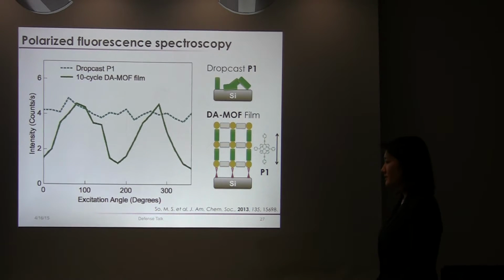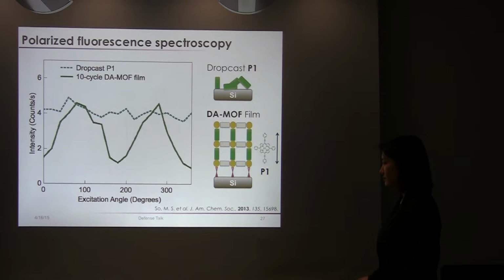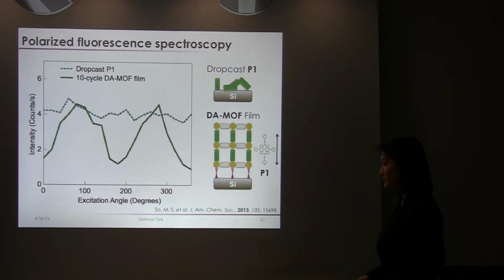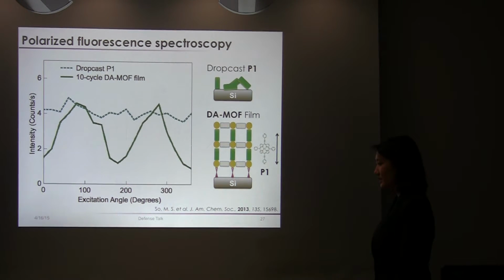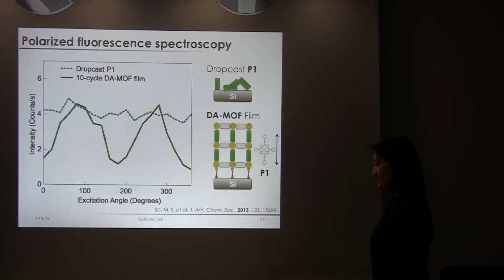So in the first couple layers, I guess between 0 to 10 cycles of film growth, by SEM I see just regions of nucleation. But after that, this film growth merges into a film growth region. So after that, I see that more homogeneous film growth is occurring on the surface. So that disorder does not propagate.